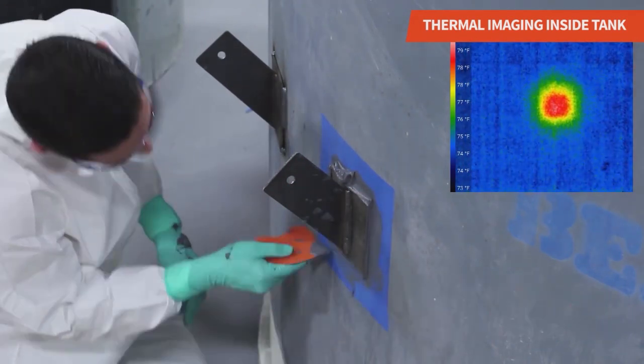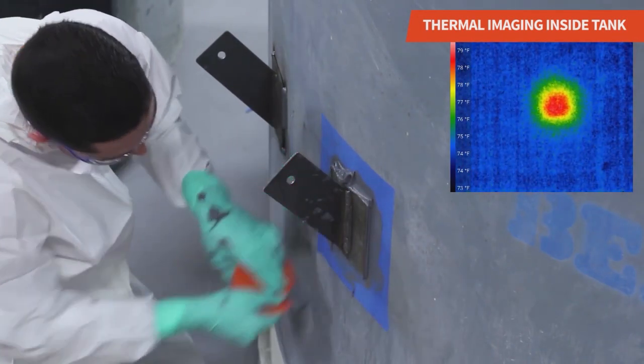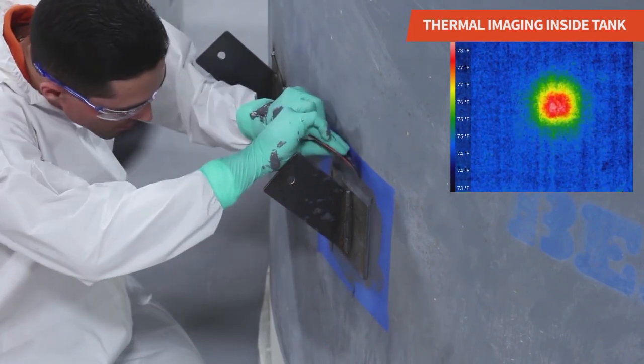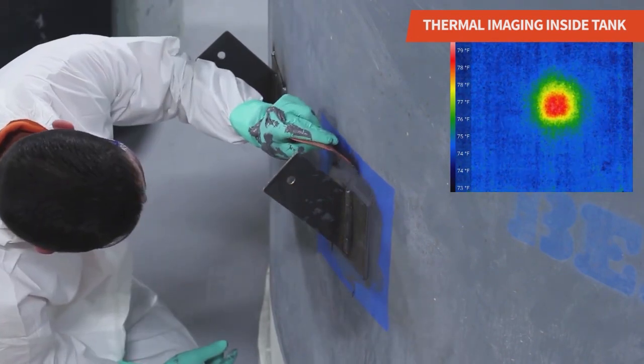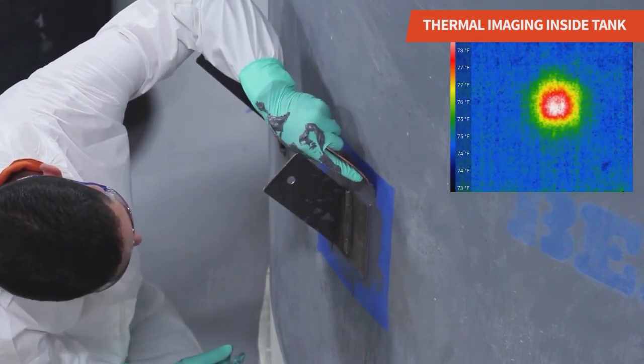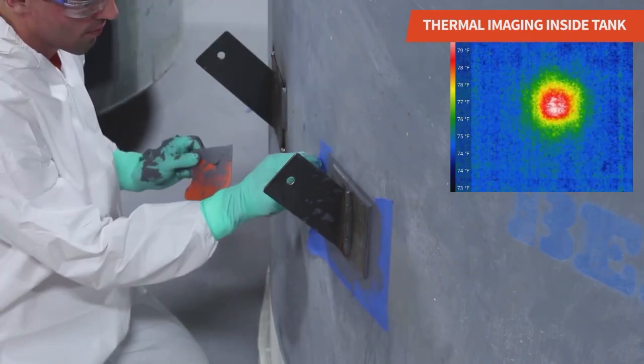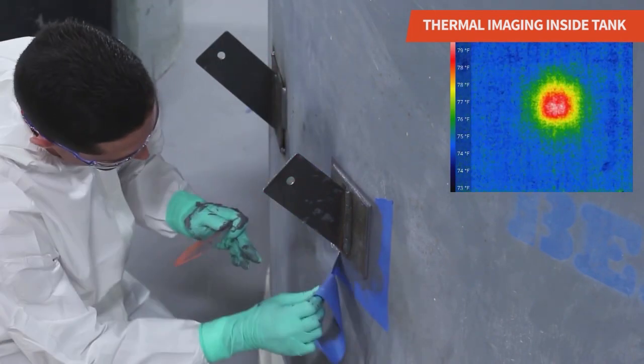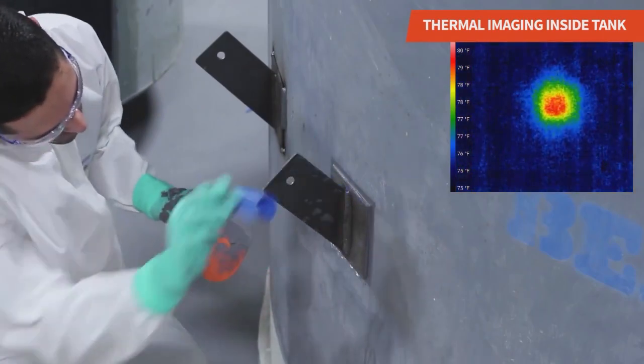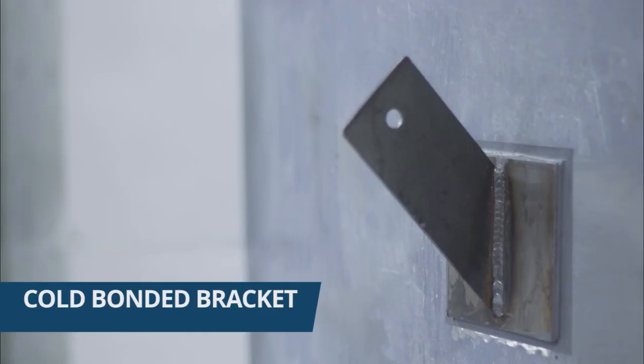We took temperature readings via thermal imaging, as you can see in this video. A maximum of 80 degrees Fahrenheit was reached, which is safe for both the tank lining and content. And we removed the masking tape to finish the application. Cold bonding is a more practical and safer choice.